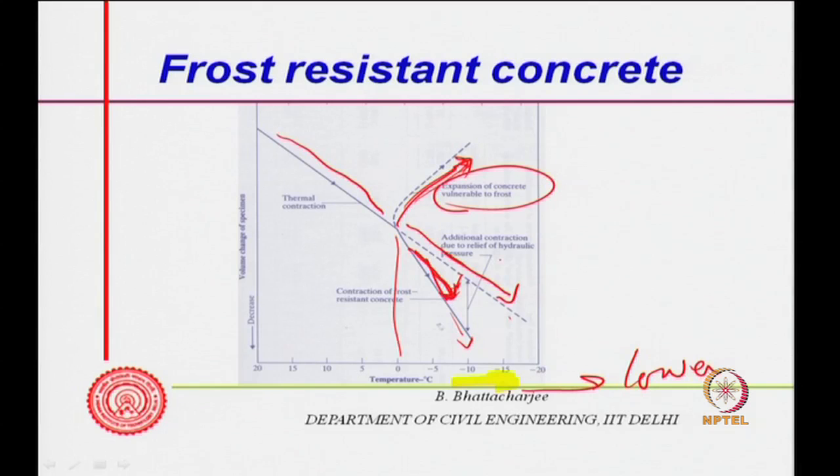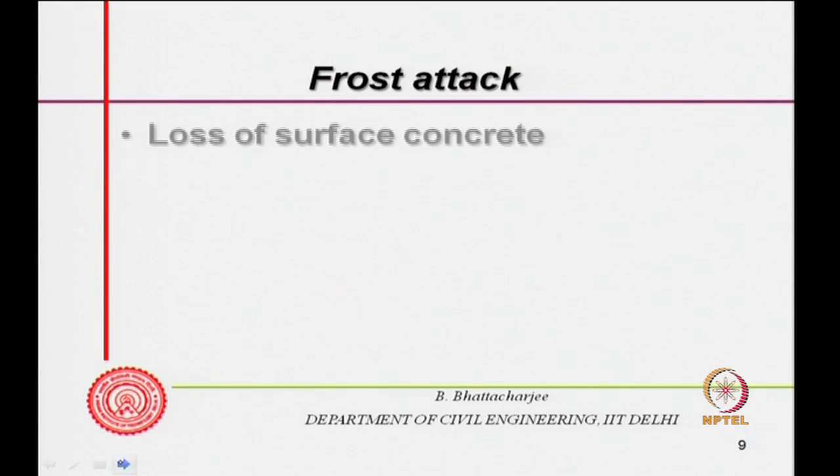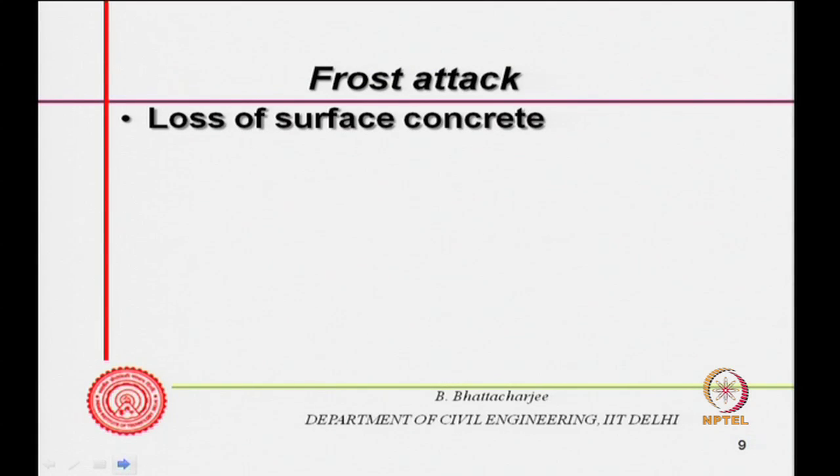So, there is additional contraction because of the relief of the hydraulic pressure. Since there is no pressure, some pores will be filled with ice, and the contraction of ice will also take place. This all results in volume contraction instead of volume expansion of air entrained concrete. So, that is protection from frost attack. Essentially, the effect is loss of surface concrete.